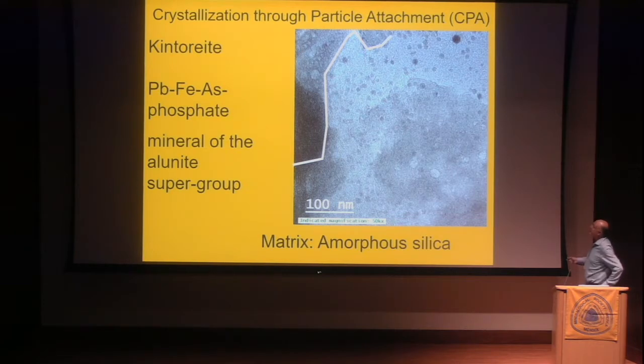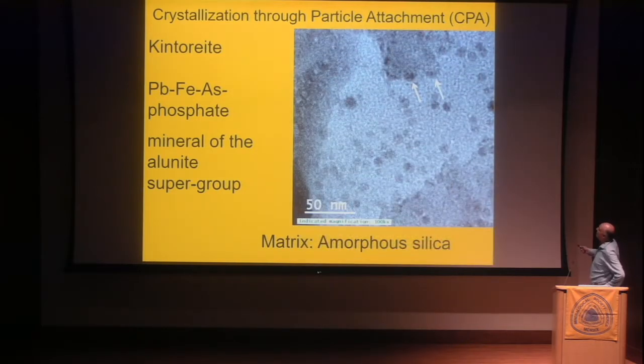So what we see here is the mineral kintoreite, a lead iron arsenate from the alunite supergroup, and it occurs in an amorphous silica matrix shown here, and you see those nanodots here. And when we take a closer look, you can actually see those nanodots, most likely of this lead iron arsenate, diffusing through the silica layer and attaching to the surface of the growing kintoreite mineral. This process is called crystallization through particle attachment. We have here the growth of the mineral through the nucleation of nanoparticles and their attachment to the mineral surface.